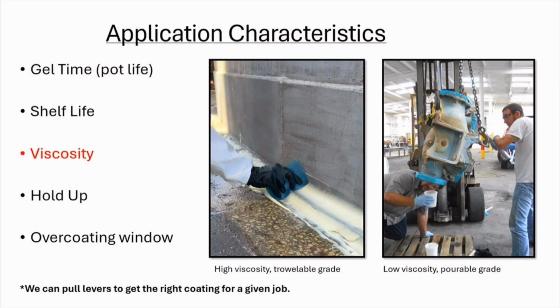The idea is that we can pull those levers to make given variations of the same coating so that it's effective to use. Hold up, that's whenever you're spraying or brushing. How much will it hold up? What's the thickness that it's going to hold up vertically? We have coatings that will hold up at 40 mils or 1 millimeter before they start to sag. In certain temperatures, we can go much higher than that even.